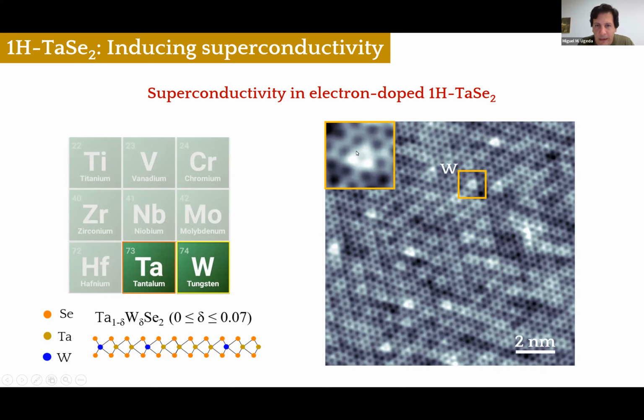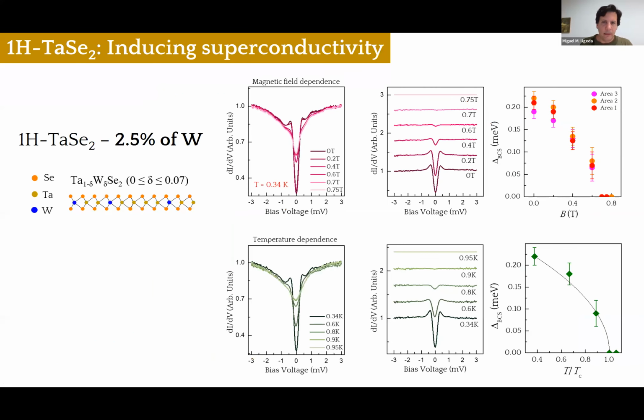The way we can identify the tungsten atoms is this fingerprint of a tungsten atom in the tantalum plane. Even when we see the selenium atoms, because we are on top there, we see triangular features that reflect the fact that the 3 selenium atoms bonded to the tungsten have a different density of states, and therefore they are different from the rest of the selenium atoms. And here we can count individual atoms, 1, 2, 3, 4, and that's how we can estimate the overall concentration of tungsten. So here I'm showing you the magnetic field dependence and the temperature.